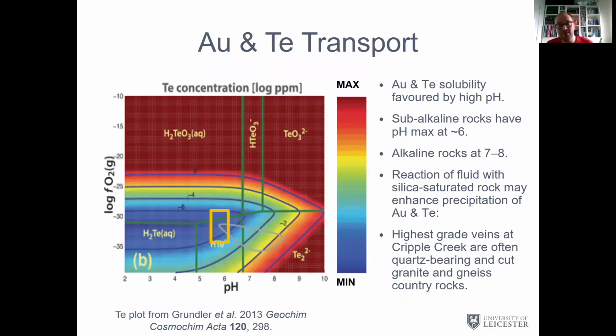So essentially, most epithermal deposits do not move tellurium around. They cannot focus it, they cannot concentrate it, and therefore they cannot precipitate it into volumes of rock at higher grades. Our alkaline hosted deposits still sit in gold bisulfide stability fields, so they can move gold around, but they are orders of magnitude more capable of moving tellurium around in their fluids. So it's the host rocks that can actually produce an important effect of moving gold and tellurium at the same time and allowing them to co-precipitate. Now they're co-precipitated, we have to find a way of getting them apart.